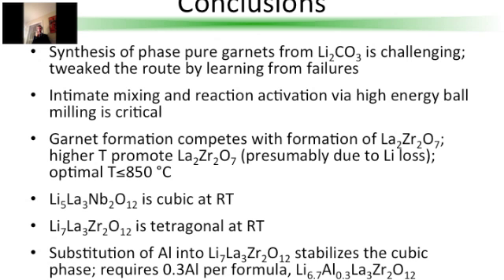So, from the work I conducted this summer, I was able to conclude a number of things regarding the optimum synthesis routes for lithium lanthanum zirconate and lithium lanthanum niobate. The first thing I was able to conclude was that the synthesis of phase pure garnets from lithium carbonate is very challenging. As you probably saw when I was describing the results, it took many adjustments to the process to finally obtain phase pure cubic structures of the two materials.